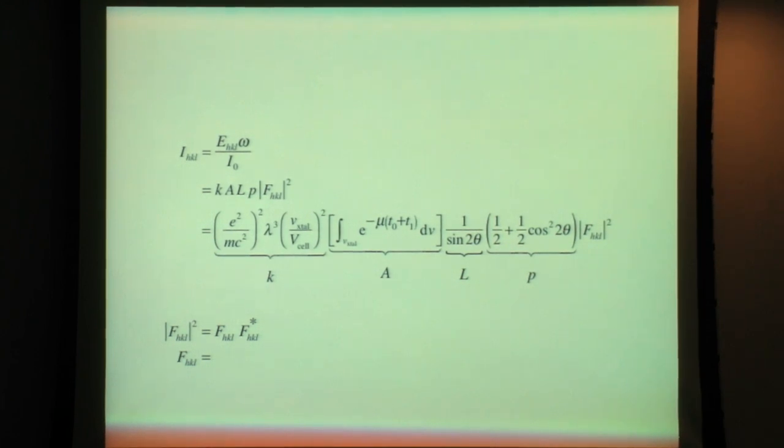This is the Lorentz factor. It has to do with how long it takes the reciprocal lattice point to pass through the Ewald sphere. Now, the Ewald sphere, we can imagine, and we will go into this later on, has a certain thickness. It's not just an ideal Euclidean sphere. Why? Because there's a range of wavelengths in the incident beam, a narrow range, but it's not strictly monochromatic radiation. Why else would it take time for the crystal to pass through the Ewald sphere?